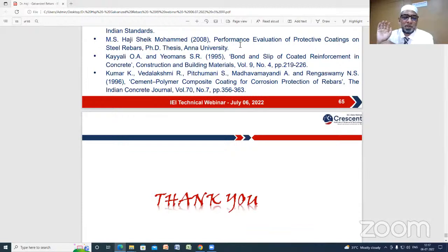And from Mr. Dhanapal and Radhakrishnan: can we make threading in galvanized rebar for coupler bars? If you do threading, definitely the galvanized coating will go off. In that case, you have to apply some epoxy coating over the threaded portion alone. Otherwise, the threaded rebars can be fabricated first and then subjected to galvanized coating to avoid the damage.